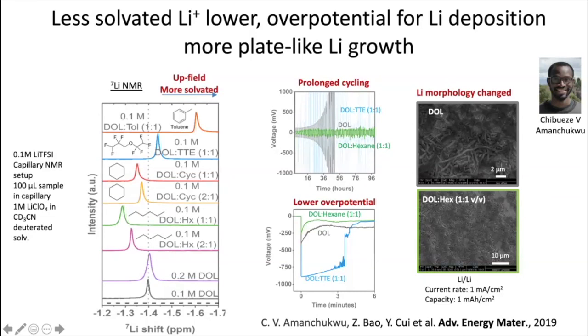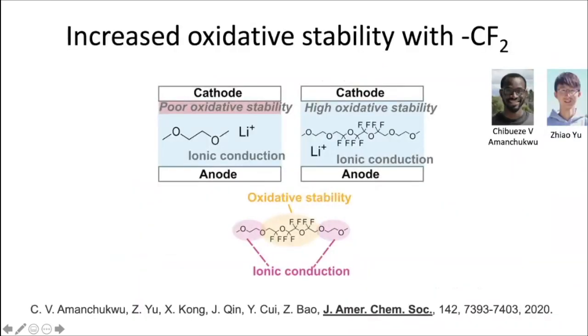Towards the right side is the upfield shift of the lithium peak in NMR, and that's the more solvated case. So we see that the solvation of lithium is very sensitive to the composition. Even the ratio between the DOL and the hexane ratio can significantly change the solvation. In general, we found that in the more solvated case, we have higher overpotential, but in the less solvated case, we have lower overpotential, a longer cycling time, and a smoother deposition. So that provides one piece of information: less solvated lithium might be desirable for improving the stability.